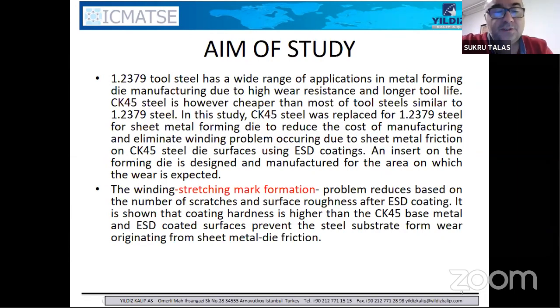But what we wanted to do is that in a die, there are regions that you're not using fully. So the disadvantage of cheap steels or less alloyed steel is that the hardness is not that high, but it's not a big problem. The problem is stretching or wearing, especially in some parts of dies. They are very susceptible to wear, especially where the sheet metal is running on the die, corners or small angle parts. These are very important design problems which you cannot overcome.